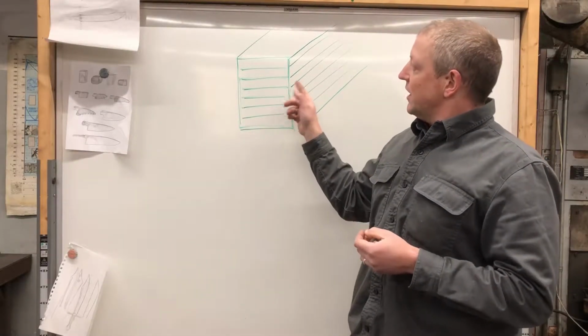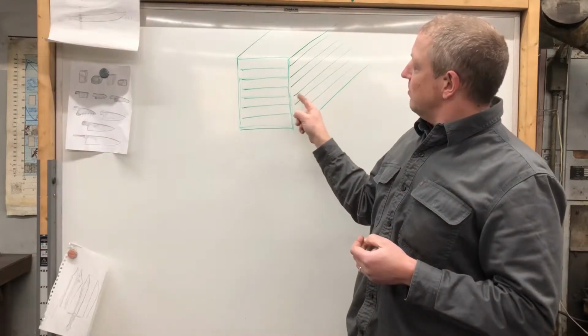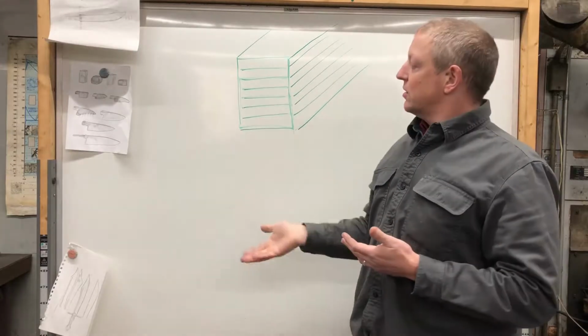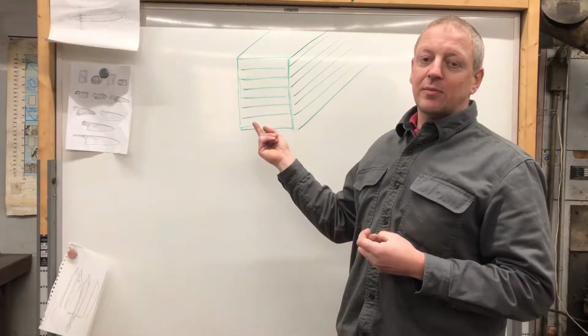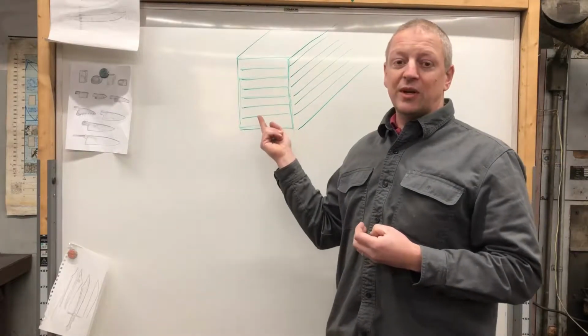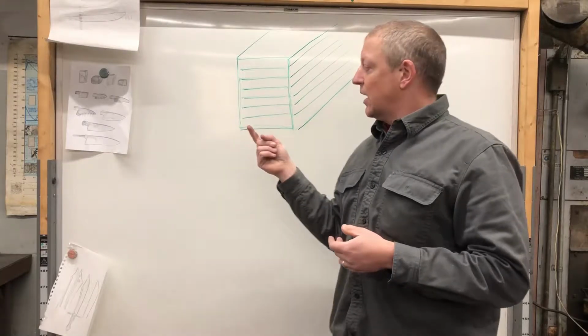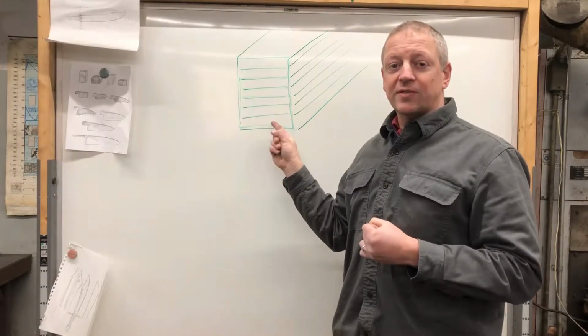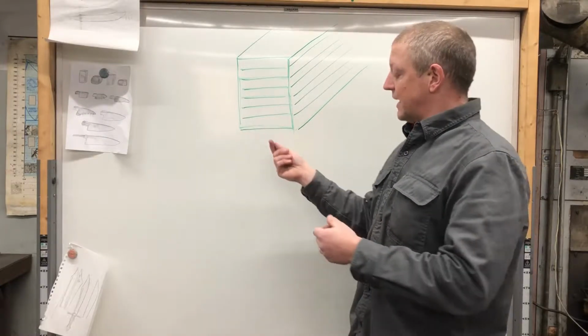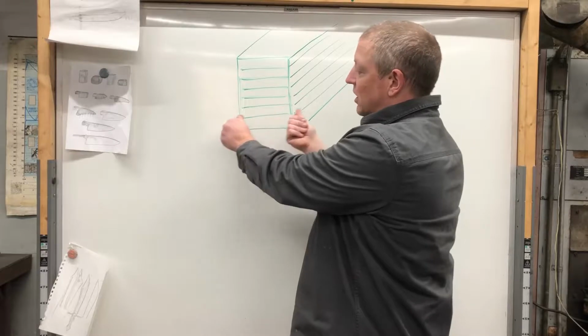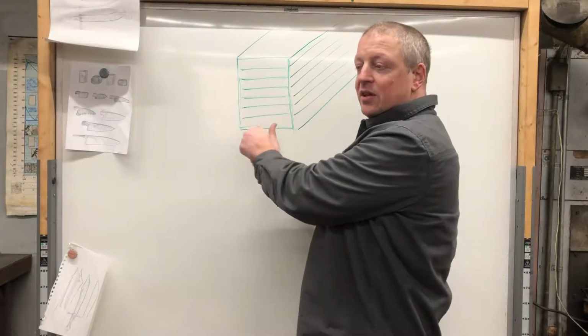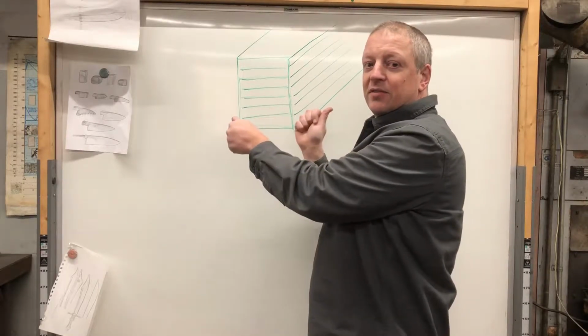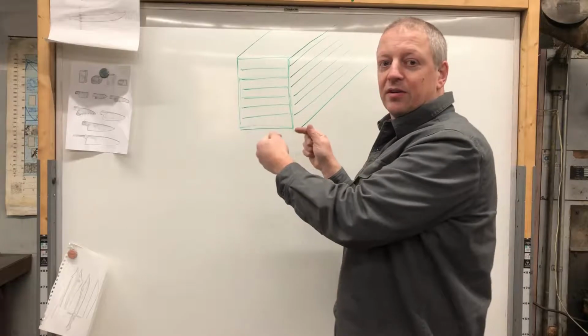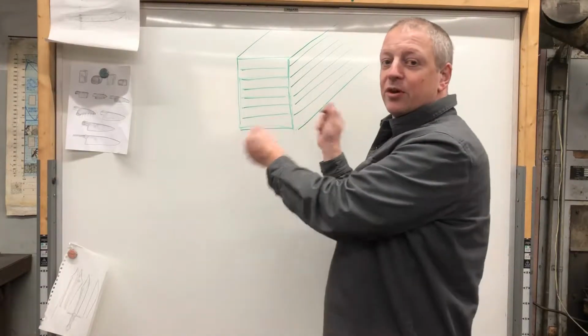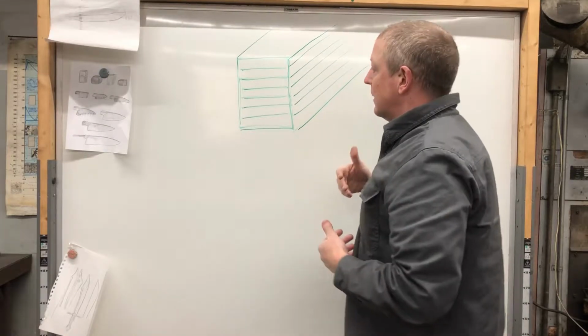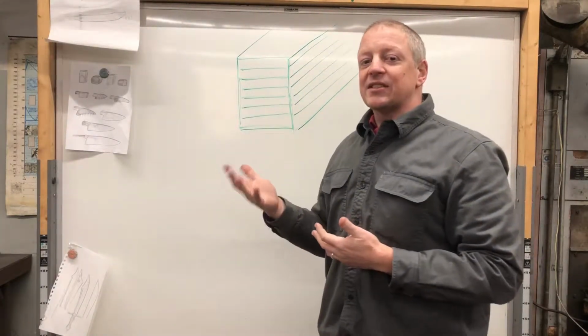So if you've got oxidation happening on the outside and to some degree making its way in, the hotter your steel is, the faster carbon is coming to the surface. And what that does is, not only does it react with the gas, sorry about the furnace noises, not only does it react with the oxides on the surface, creating that carbon monoxide gas, but now you're creating pressure between the layers. You have positive pressure of that gas floating out, keeping oxygen from penetrating, keeping that forge atmosphere from penetrating between the layers. So your steel cleans itself.